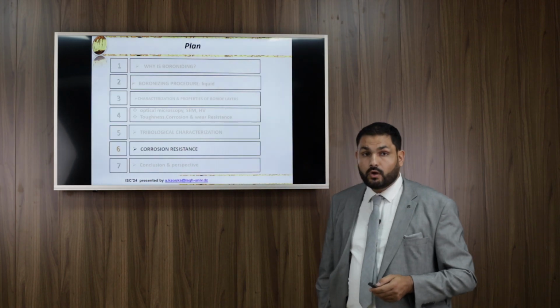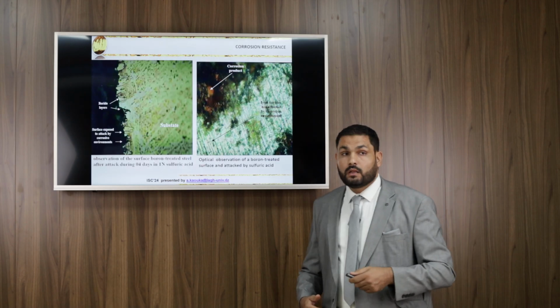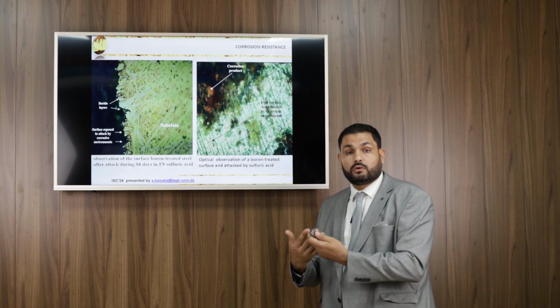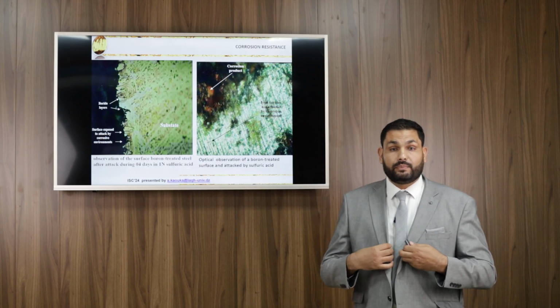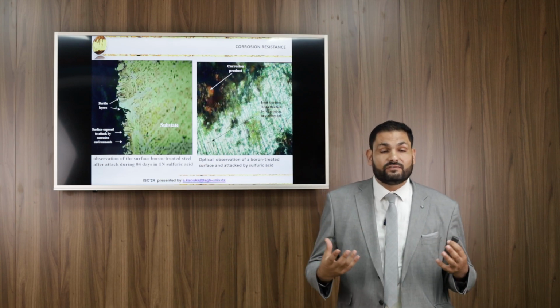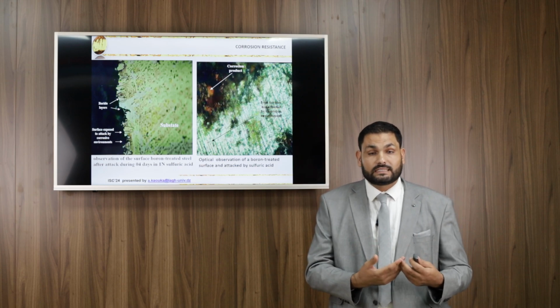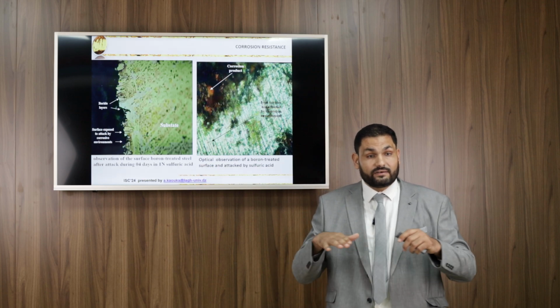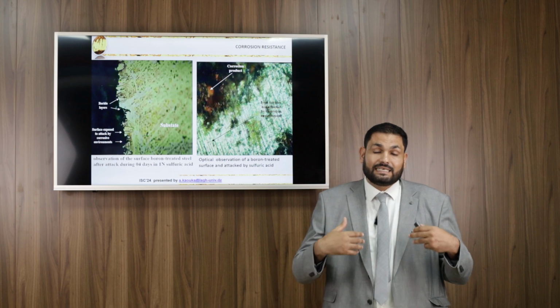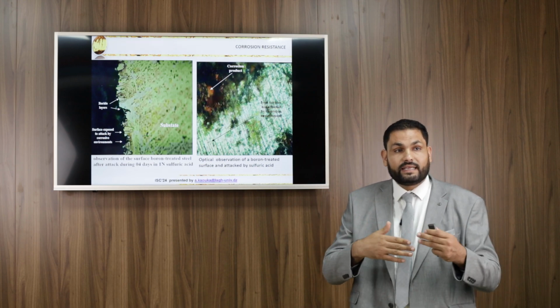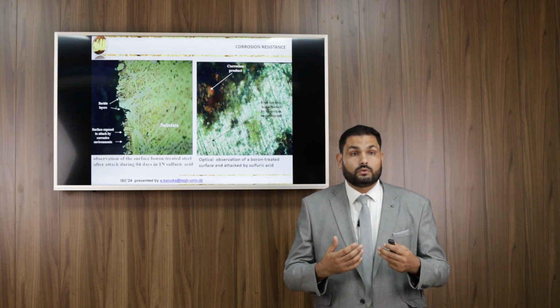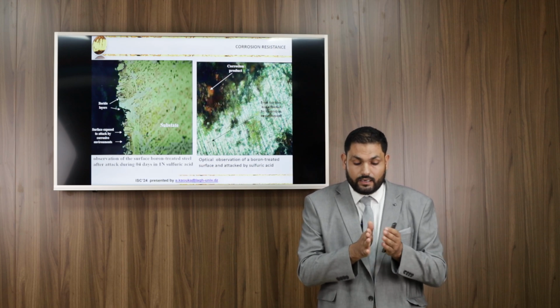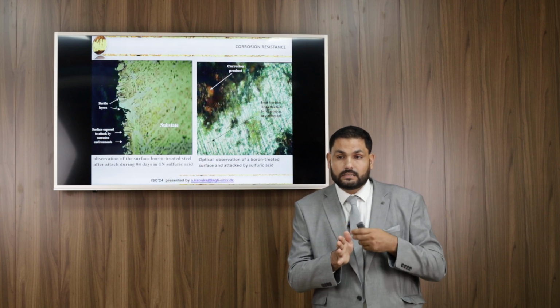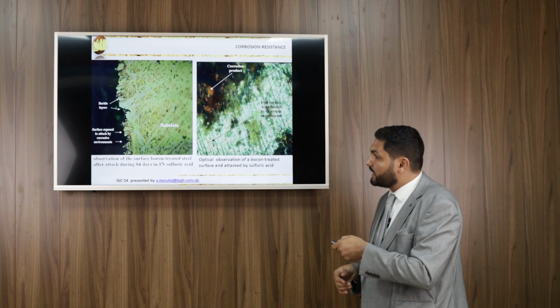With EDS analysis, we have the micrograph. In red color is the titanium, and in blue is the boron that we confirmed with EDS. For corrosion resistance, we found that the boride layers improve and enhance the properties in aggressive environments, hydrochloric, sulfuric and nitric acid, due to the barrier formed by the boride layers. The barrier works due to its compactness and no reaction between the environment and the boride compound.